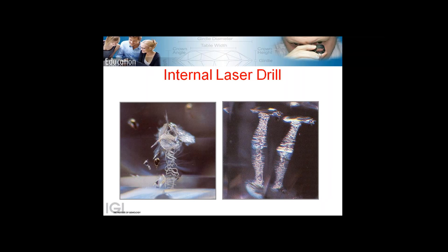So what's happening is they're creating a feather inside the stone so that it looks like a very natural inclusion, but they're trying to remove the color. Probably this was a completely black, dark included crystal in the stone. So a crack has been created by the internal laser, which starts from the surface, reaches the inclusion, and then they simply boil the stone so the color of the inclusion gets bleached.